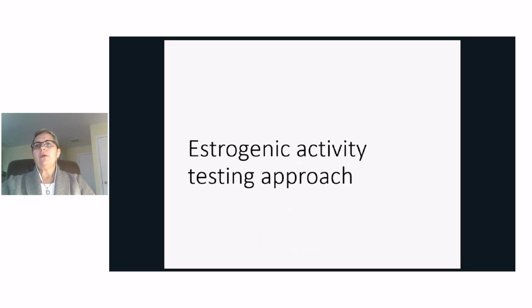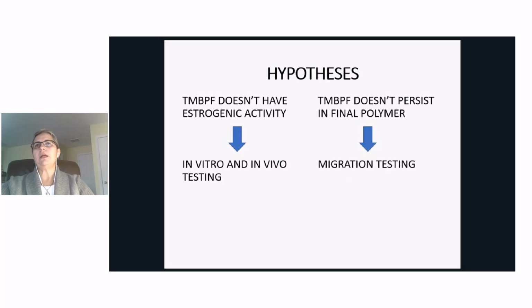So far we have a polymer, and we have the functional structure needed for its performance. So now we need to test whether the monomer has estrogenic activity. The hypothesis was that based on modeling, it would not have estrogenic activity, and it would not migrate because, as I showed you earlier, TMBPF is formed and reacted immediately to form the polymer. So the expectation is that there won't be migration or residue.